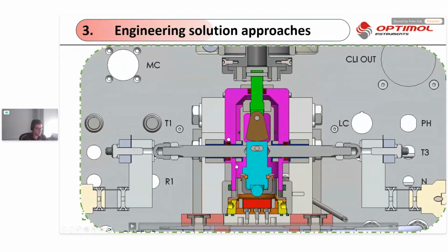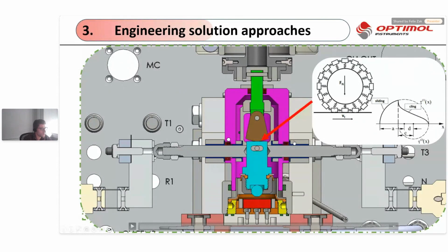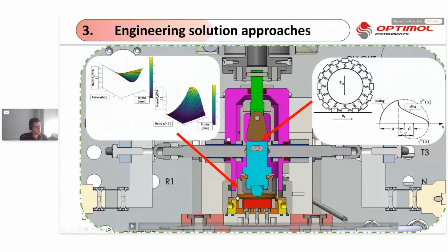When we apply such a mechanism, we also need to take into account some contact mechanics here for the pendulum, to make sure that the initial wanted movement is correctly led to our contact down here. And also our bellows here, which separates the hydrogen and the nitrogen space, will cause a parasitic force, which we need to be aware of, like Mirko mentioned, that such parasitic forces can change the signal of the friction, and to get clear and comparable results, we need to account for that as well.